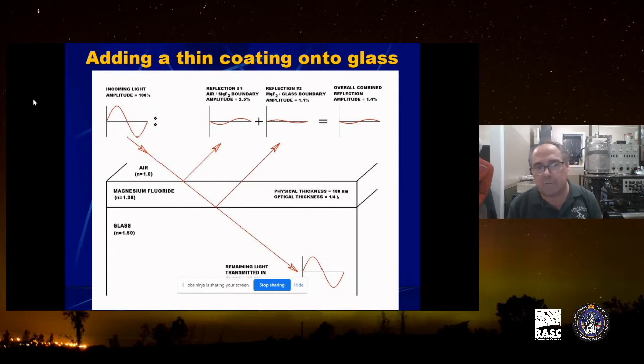But as you can see, the light is traveling into the magnesium fluoride a quarter wave thick, and it's exiting out of the magnesium fluoride by another quarter wave. So now it's a half a wave out of phase. And so we have two reflections that are out of phase with each other, similar to the bulbous bow. When you add them together, you get a resultant reflection that's only 1.4%. So we went from 4% from bare glass to now 1.4% reflectivity by just introducing a simple thin film coating, such as magnesium fluoride. The same thing happens on the back side of the glass. We have the same coatings there, and of course we get a much better improvement in light transmissivity.